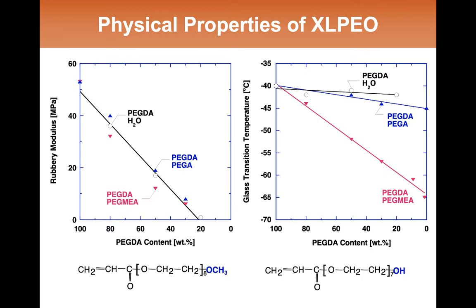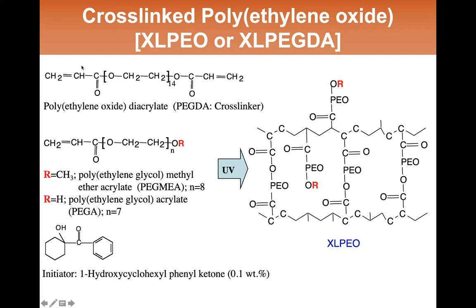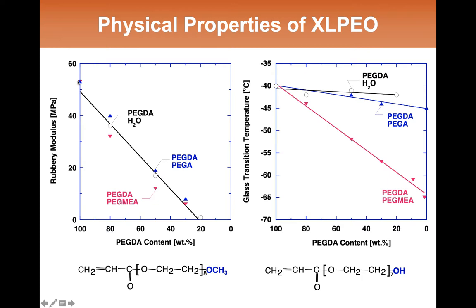They're flexible, squishy membranes. And what's being shown here is that as the concentration of the cross-linker, that is the PEG diacrylate, which is the material shown at the top of this slide, decreases, the mechanical properties, the modulus, goes down. And this reflects a decrease in cross-linking density. The way that the cross-linker content is decreasing is being brought about in three different ways in this graph.